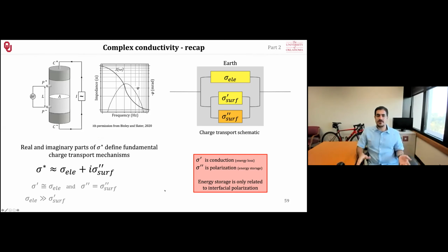Just a recap on complex conductivity. You measure the polarization and also the conduction at the surface and the electrolytic conduction through the pore filling fluid. So in here, again, if you have pore spaces getting smaller because of the compression, for instance, the ions can travel in a shorter time, so you would have a different signal than at the initial time. So it's important to use complex conductivity.